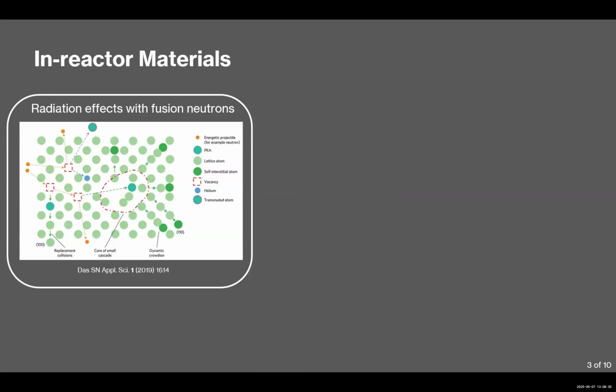For example, a neutron can come in and hit our nice crystalline material. All of our hard work, forging, melting, heat treating, we spent so much effort making this nice omelette, and then the neutron comes in and just turns it into scrambled egg. So it comes in, it can knock atoms around, it can transmute atoms where the neutron is absorbed and turns into something else, which has a lot of knock-on effects, but there's a lot of extra stuff that can happen inside a material that can degrade it.